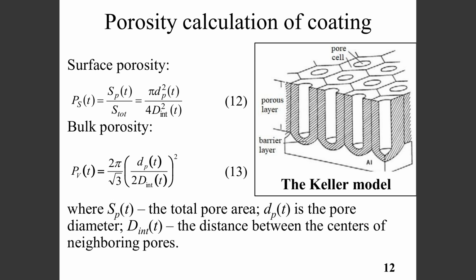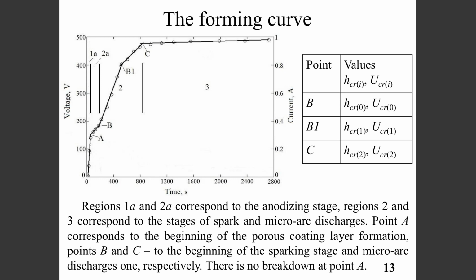Surface and bulk porosity of the coating at the anode stage is calculated based on a geometric consideration according to the Keller's model. Based on the available empirical formulas and piecewise linear approximation of the experimentally measured time dependencies of the forming voltage, called forming curve, a recursive algorithm that allows to calculate the thickness of micro-arc oxidation coatings at the stage of microdischarges starting from the sparking stage is obtained. The forming curve of the micro-arc oxidation process is presented on the slide. Regions 1A and 2A on the graph correspond to the anodizing stage. Regions 2 and 3 correspond to the stages of spark and micro-arc discharges. Point A corresponds to the beginning of the porous coating layer formation. Points B and C to the beginning of the sparking stage and micro-arc discharges respectively.